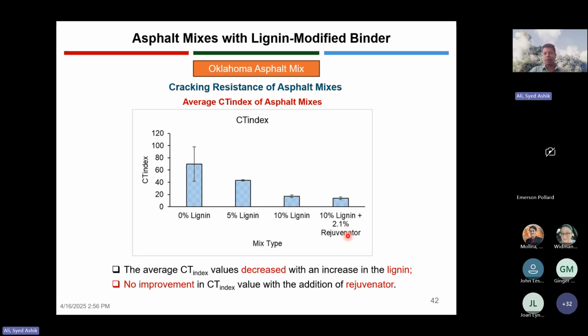And so our idea to add rejuvenator was to see whether adding rejuvenator can increase the CT index value. But we have seen that although the mix is not as stiff as the 10% lignin, the addition of rejuvenator did not help much in increasing the CT index or cracking resistance.